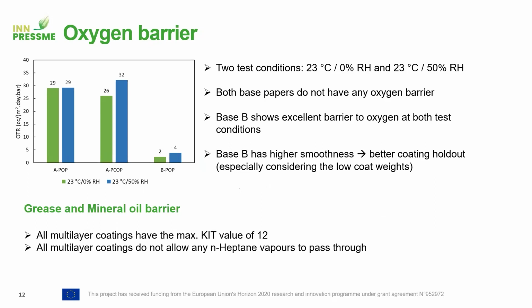Then to the oxygen barrier. We tested two different conditions, 0% relative humidity and 50% relative humidity. No references are presented here because both of the base papers do not have any barrier for oxygen. We see that the coating on base paper B has a clearly higher oxygen barrier, and this is because base paper B has a higher smoothness, so we get a better coating on the substrate. We also thought that we could increase the oxygen barrier by incorporating the CNCs, but it's approximately the same with or without the CNCs. So when we moved further to the industrial demonstrators, we made them without the CNCs. For all of these multi-layers, the gas, grease and mineral oil barrier were also very good.